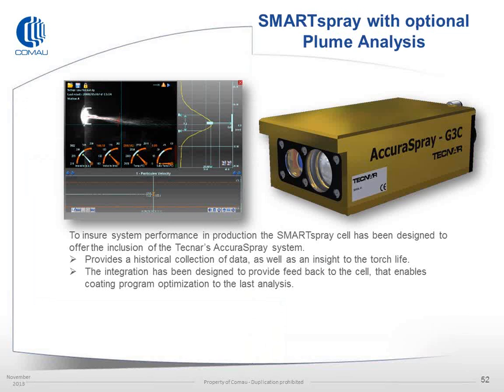As I mentioned before, we've been able to integrate the AccuraSpray from Tecnar. The ability to do this allows us, on a regular basis, whether it's every 100 hours or every hour or every 20 blocks, to bring the torch to an inspection location, run the torch, characterize and record the plume, put a feedback back into the system if there's any change in the plume direction, compensate for changes, and then continue, or even predict torch life and be able to ask for removal or replacement of the torch.